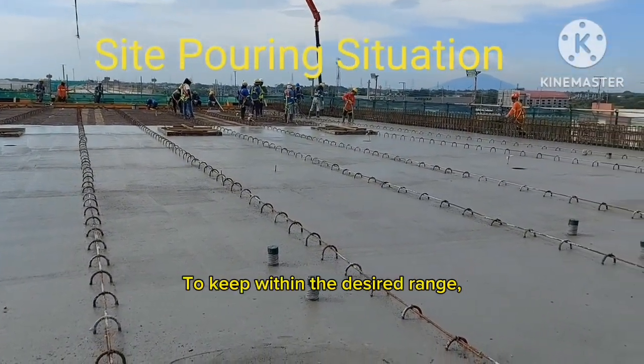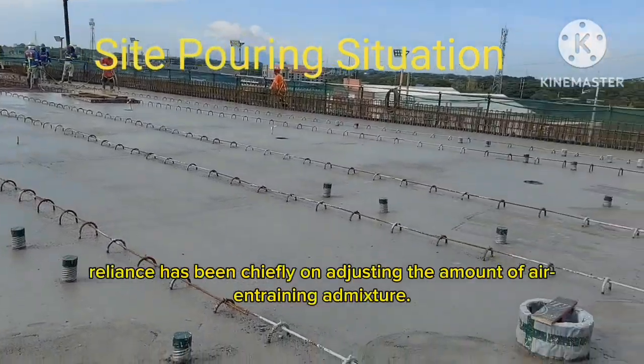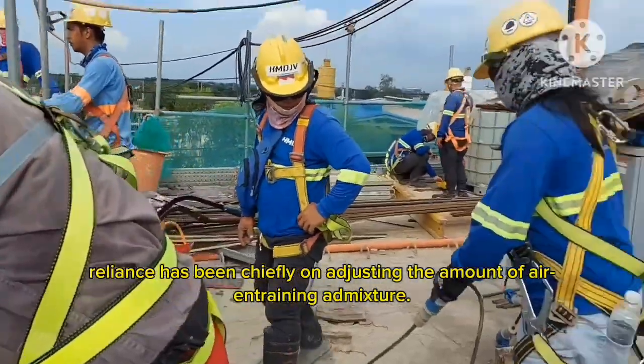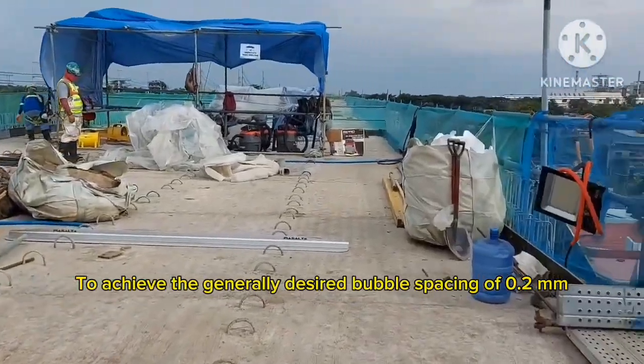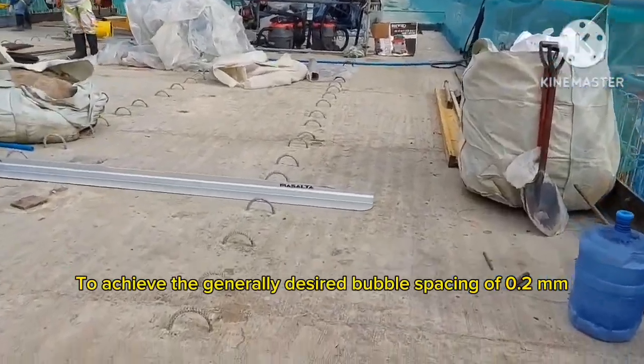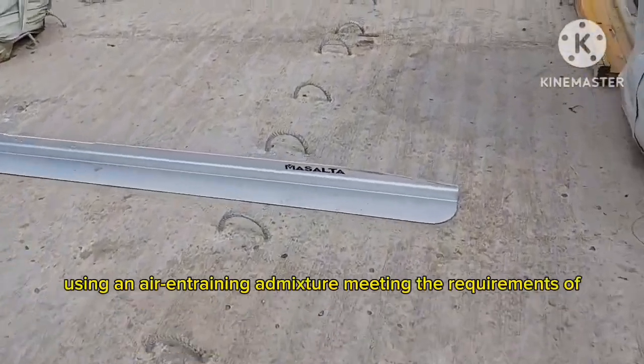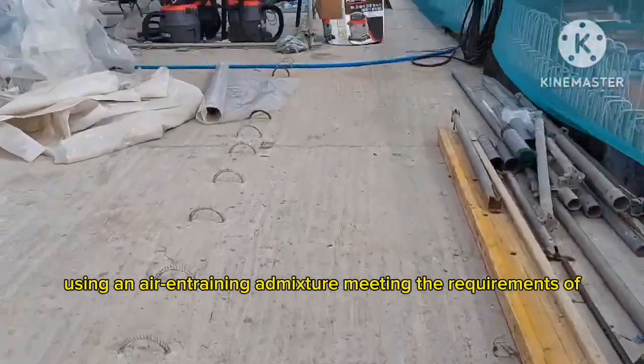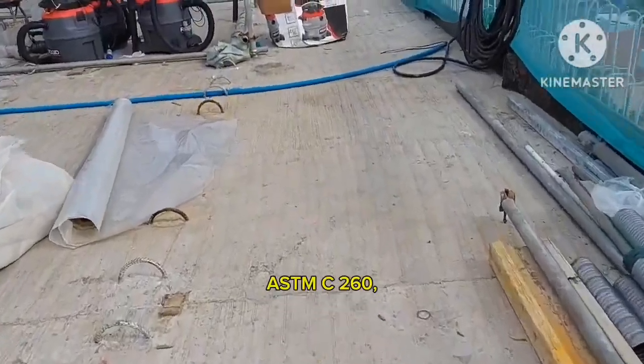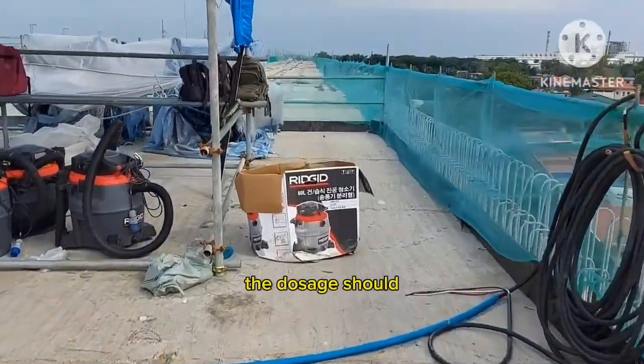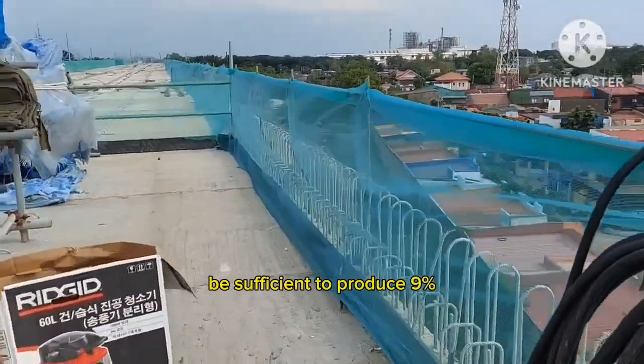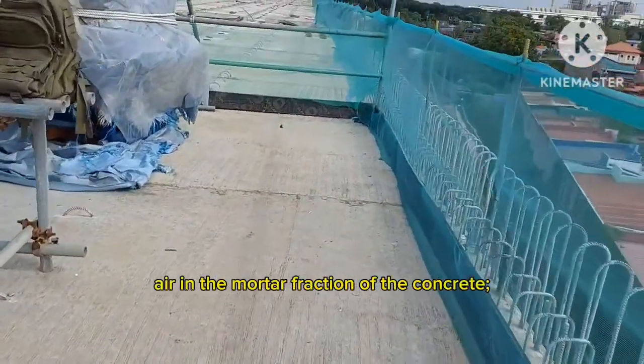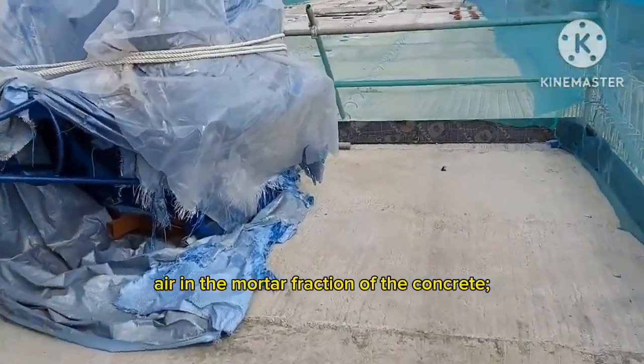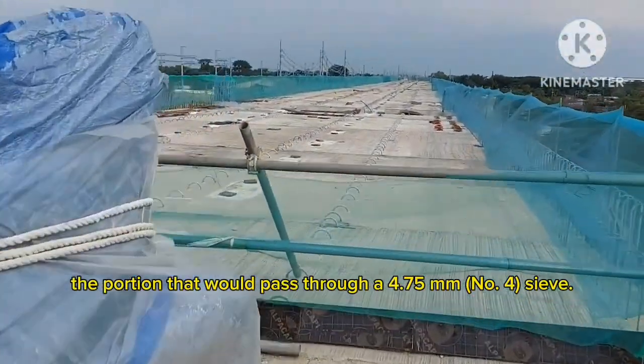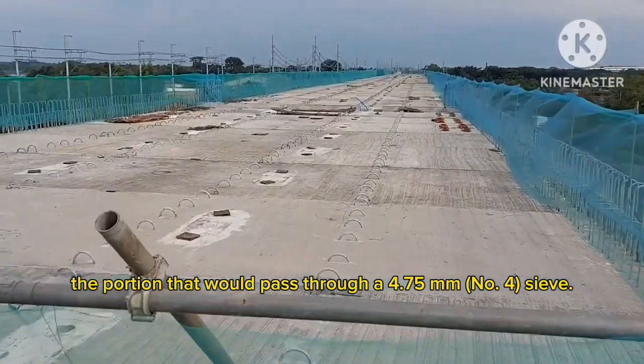To keep within the desired range, reliance has been chiefly on adjusting the amount of air-entraining admixture to achieve the generally desired bubble spacing of 0.2 millimeters, using an air-entraining admixture meeting the requirements of ASTM C260. The dosage should be sufficient to produce 9% air in the mortar fraction of the concrete. The portion that would pass through a 4.75 millimeter No. 4 sieve